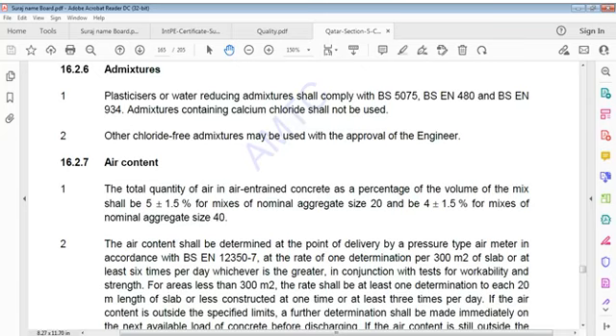Air content. Total quantity of air in air entrained concrete, as a percentage of volume of mix, shall be 5 plus or minus 1.5% for mixes of nominal aggregate size 20, and 4 plus or minus 1.5% for mixes of nominal aggregate size 40.